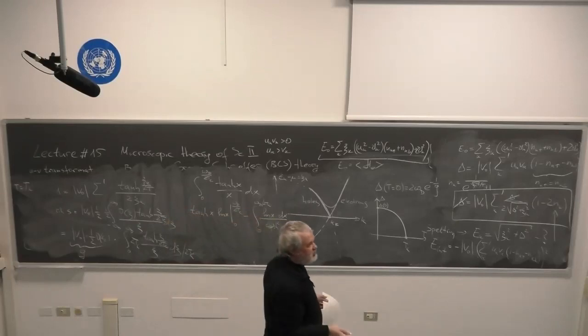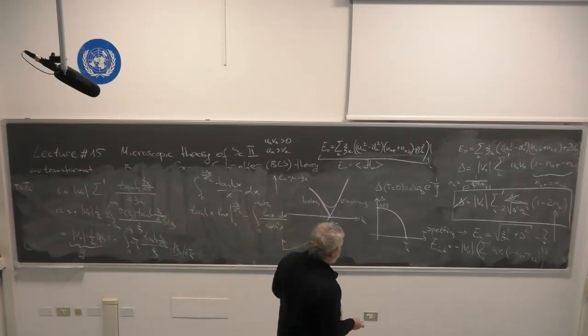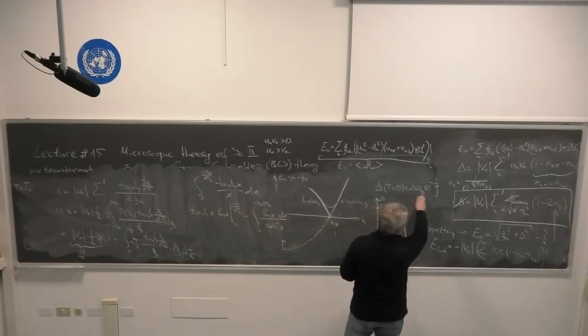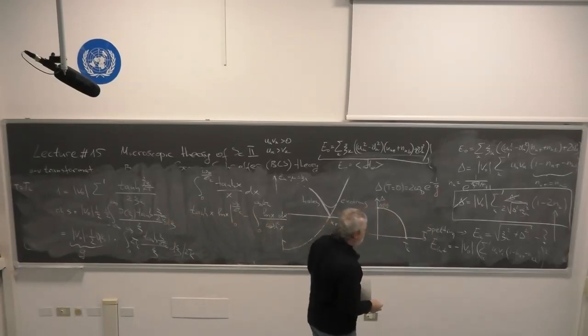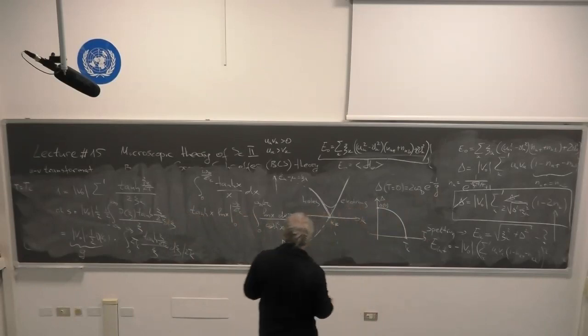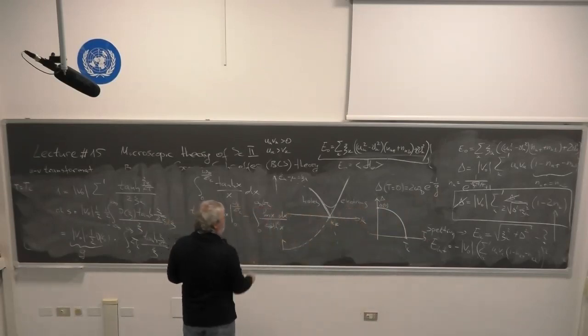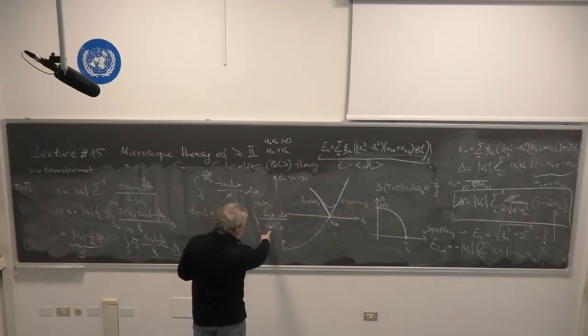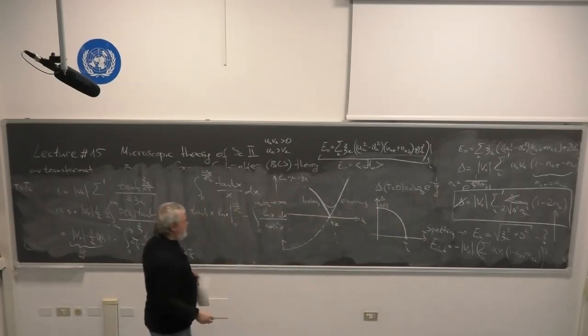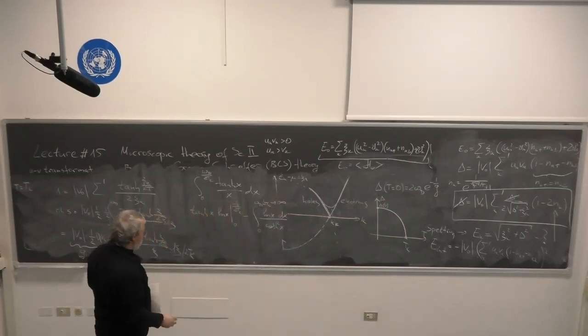My intuition tells me that the critical temperature should be on the order of the gap, and therefore it should be exponentially small for small interactions with respect to the Debye frequency. Therefore, omega d over 2 Tc is very large, and this integral converges both in the lower limit and in the upper limit because of the exponent. So without losing generality, I can put this parameter equal to infinity.